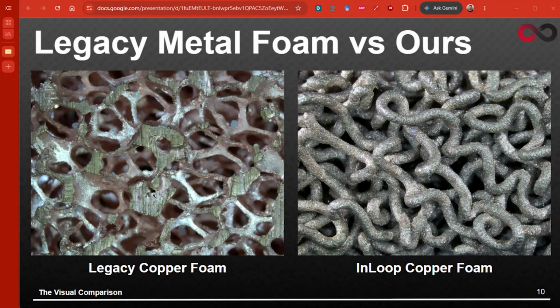But overall, the connectivity of our coil-based foams is much more consistent than legacy foams. And for mechanical behavior, there's also a really strong relationship here, where those legacy foam links, as you can see, are all straight. They're all functionally at their maximum extension from the get-go. So if you put them into tension, the only thing they can functionally do is stretch before fracture.